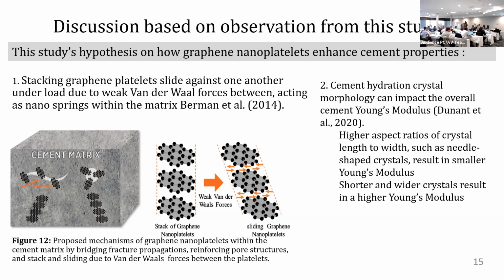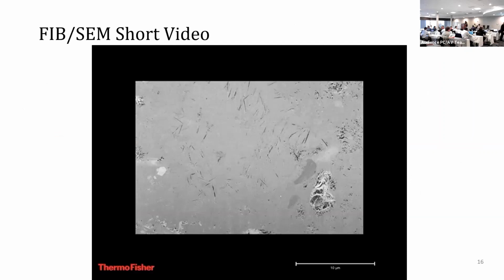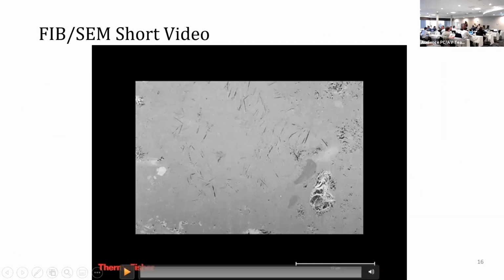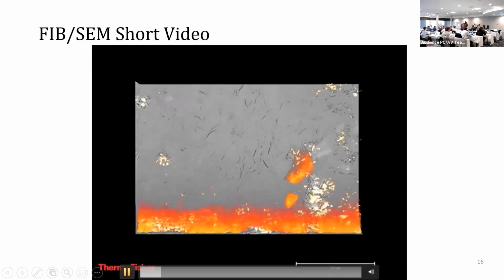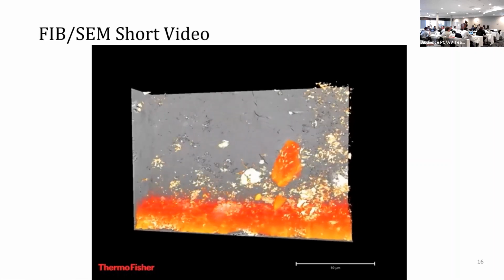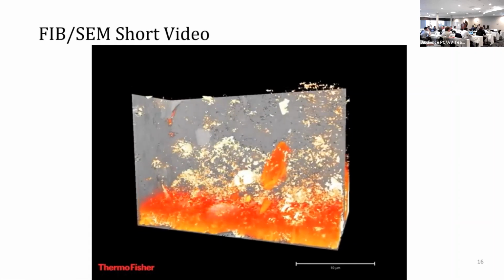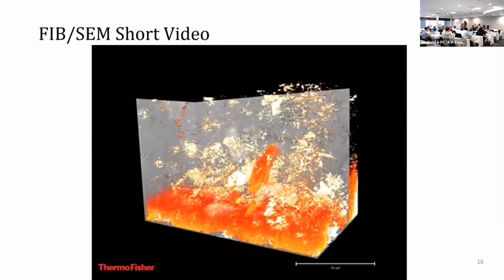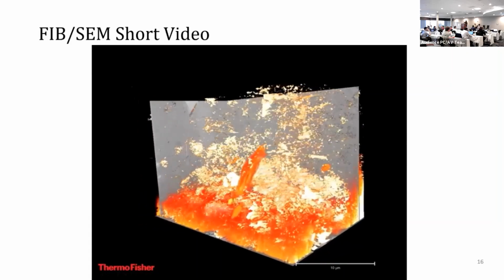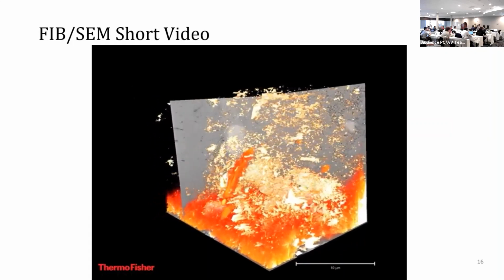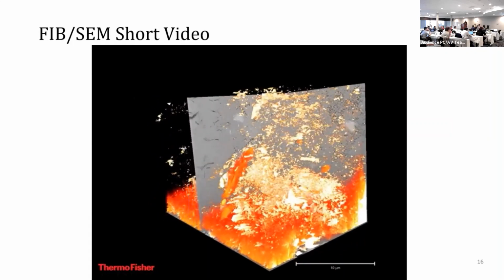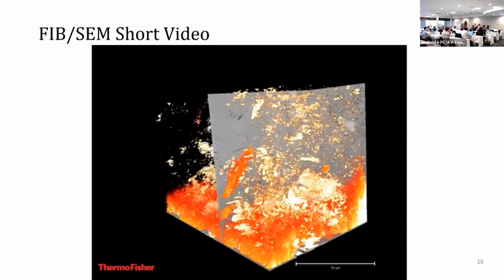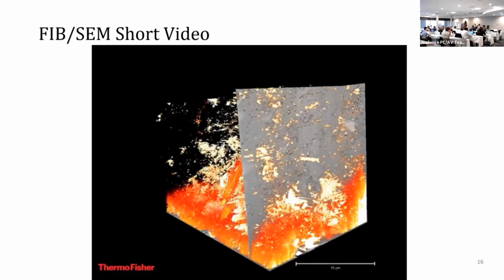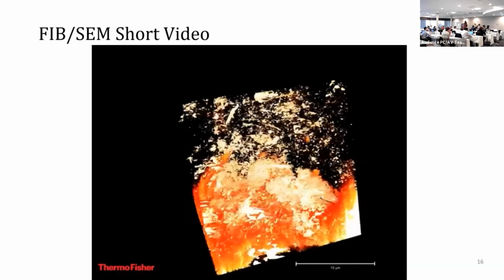In terms of cement hydration crystal morphology, as I said, I think there is a little bit of evidence in this video. So what is this? You take a small piece of cement, you put it in a focused ion beam microscope, and then you keep slicing through it. We're looking at a scale bar of 10 microns. So this whole box is maybe a 12 by 12 by 12 micron cube.